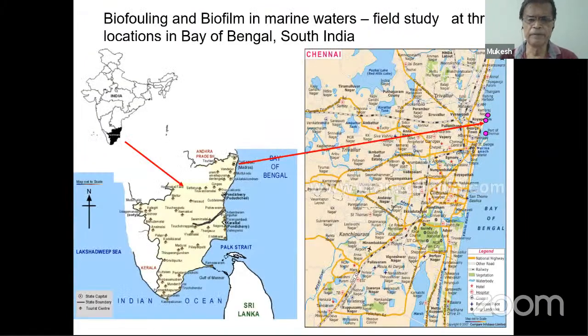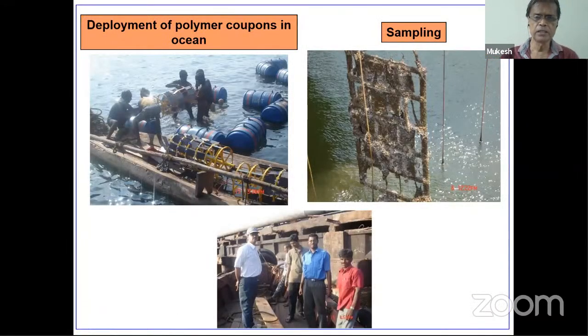So what we did later on is we put a large number of various polymer plates in the marine ocean in two different places in the Bay of Bengal. Okay, two different places, as you can see in the map, near Ennur port and near the sea, Chennai coastal region. And over a period of 1 year, 18 months, we studied how these materials, is there any degradation of this material? Is there any fouling of this material? And all these were studied. Okay, you can see these are some field pictures where we had to use divers to place all these materials in the ocean. And as you can see, we take out samples of polymers, and a lot of biofouling has taken place on our polymer samples over a period of time.